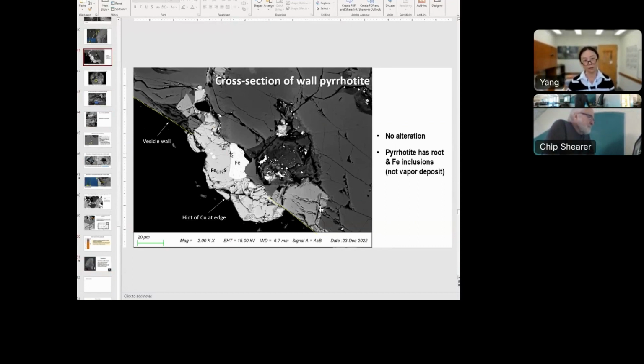Mm-hmm. Yeah, I think it seems to be following along a pathway, and in the root we do see it also appears to have some holes. The Apollo 15556 vesicles are 30 to 40 volume percent, but the porosity is actually pretty high. That's shown in that CT scan. And with the CT data, we see for some of the sulfide, not just this 2D section, in our chips, there are roots that are going from exposed in the vesicle to the rock. So it suggests some kind of ductile behavior of the sulfide.